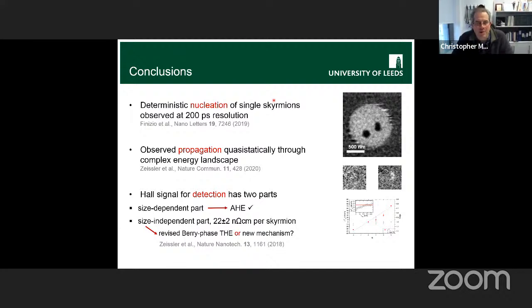Okay, so there are two things to think about here. For a certain set of parameters like anisotropy, DMI, and so on, if you do a micromagnetic simulation, you'll find there's a certain natural skyrmion size that corresponds to the point where all those energies balance out. In those simulations, you're normally dealing with a very perfect, ideal material that's totally uniform, and so the skyrmion can easily relax to find that natural size. What we found in our materials, because they're real materials with quite a bit of disorder, is that the skyrmion size can be hysteretic. There's pinning, and you can have different metastable sizes under the same conditions depending on what you just did to your system. So this is an example of that.